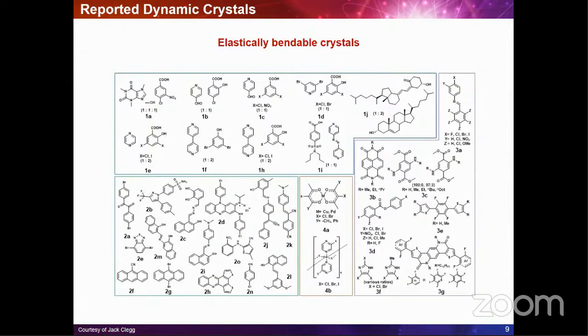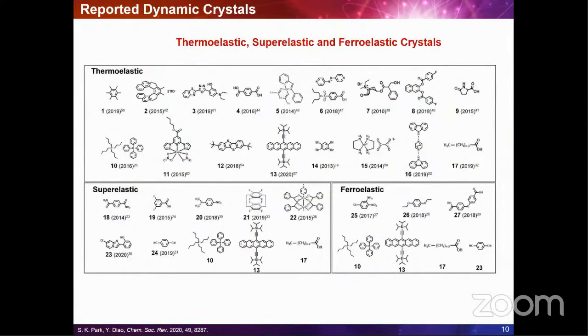And as you can see, we already have quite a few compounds, and the number of these materials is continuously growing. And this is another review from another colleague from the US, where she collected all the examples of thermoelastic, superelastic, and ferroelastic crystals. And these are increasingly important because some of them, most of them actually, are completely organic, which means that they are very soft and at the same time they are very light. So we kind of overcome the main problem that we have with metals, which is their large density, and that translates into a large or heavy weight.